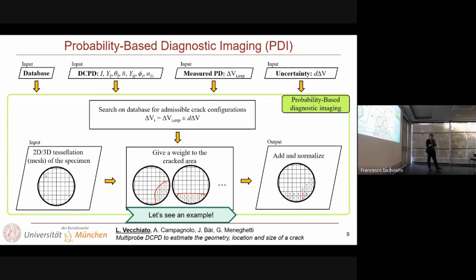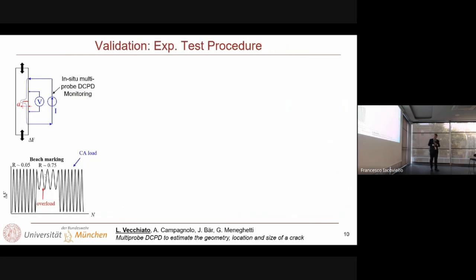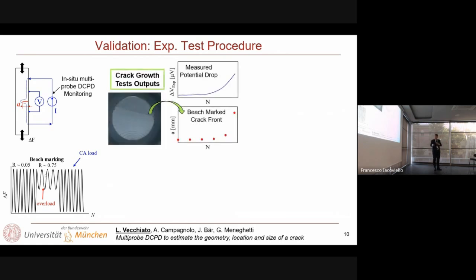And finally, we can just add all the images together and eventually normalize it, identifying a certain region of the pictures that show to have the highest probability where the crack is located and what could be the most probable shape of this propagating crack. So just to validate this model, we performed some experimental tests, just performing some benchmarking to have a clear idea what is the real crack shape on the final fracture surface.